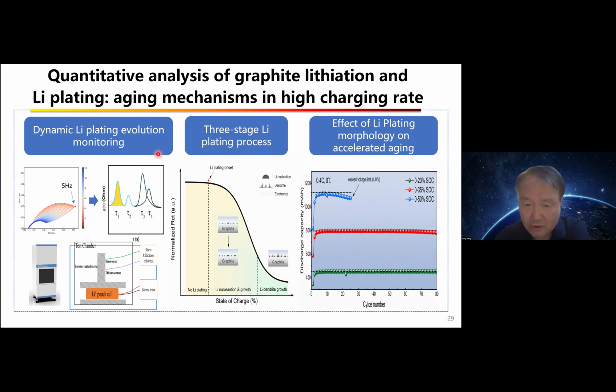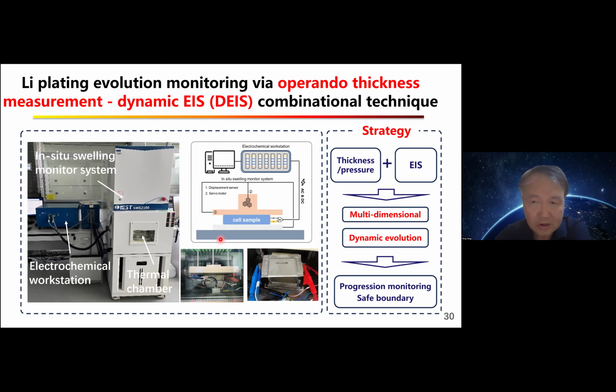So we use what we call an in-situ swelling monitor system combined with an electrochemical workstation, that's the thermal chamber. We try to use EIS and thickness pressure measurement to construct multi-dimensional techniques to follow the dynamic evolution of the lithium plating.